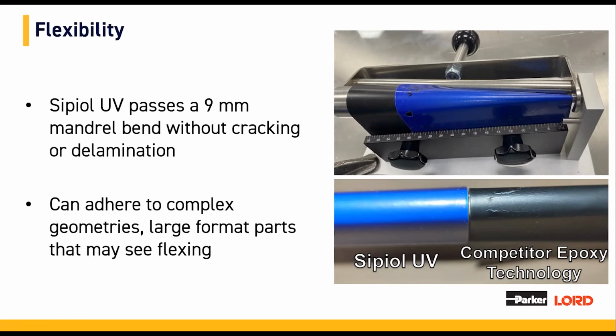This is in stark contrast to many epoxy coatings, which can exhibit cracking when exposed to flexing or mechanical stresses. Note the image on the right comparing Sipiol UV to a competitive epoxy using the mandrel bend test. You can see cracks in the epoxy coating, exposing the metal substrate underneath, thus eliminating any electrical isolation properties. This high flexibility allows Sipiol UV to coat complex geometries and large format parts, which may see flexing or warping during use.